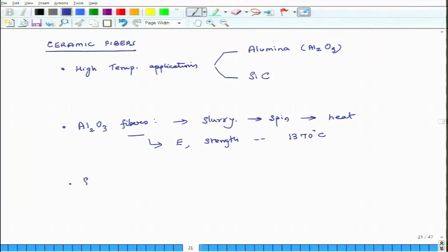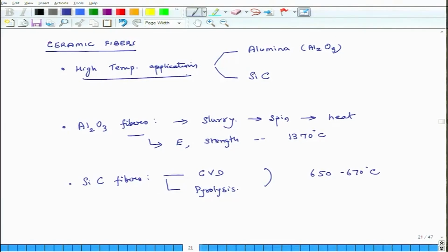About silicon carbide fibers, these are either made from the CVD process, which is chemical vapor deposition, or they are made from the process known as pyrolysis, and we have discussed this earlier. And these fibers, they can retain their strengths up to 650 to 670 degrees centigrade. Where do you use these? So, I have already said that you use them in high temperature applications, but what kind of applications are there?